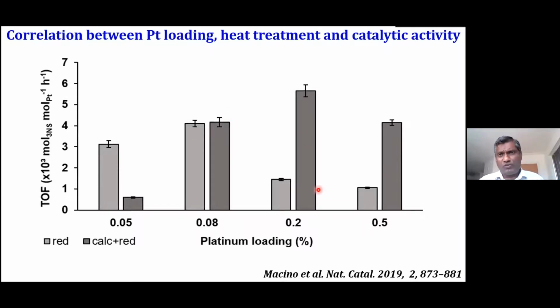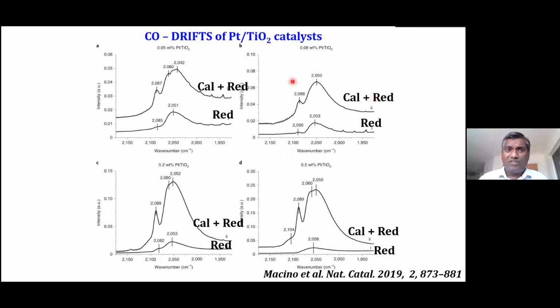So this shows size-dependent A-SMSI, which was not very well known at that time. A-SMSI is dependent on size. As you can see, the best technique to study A-SMSI is CO chemisorption or CO DRIFTS.